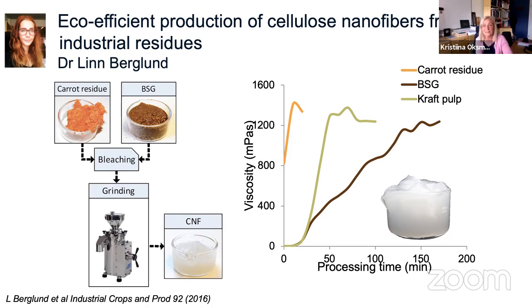And in this picture, you can see this carrot fibers. We have this brewery spent grain, and then we have also kraft pulp as a reference material. That is common pulp from a paper mill. And what you can see here is that for this carrot material, the viscosity is increasing very fast compared to the other ones. That means that we are doing this fibrillation very efficiently. And at the same time, you can see that this brewery spent grain, it's very difficult to come up to a high viscosity level. And this means that it's difficult to fibrillate that material.